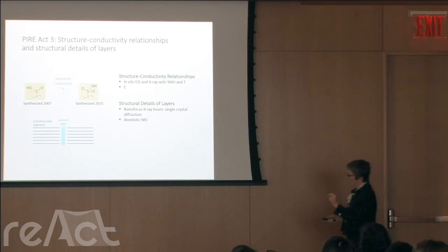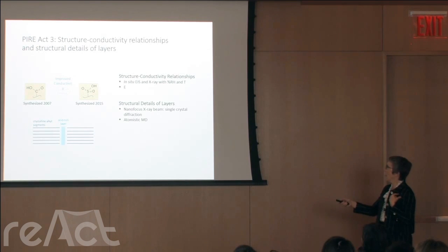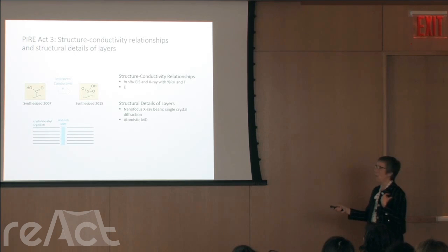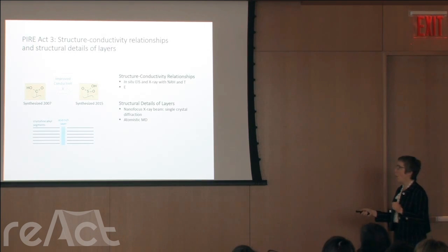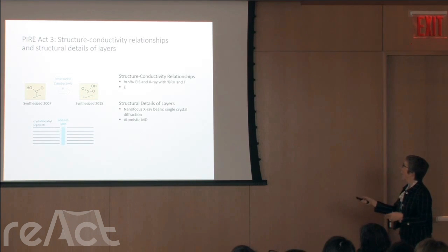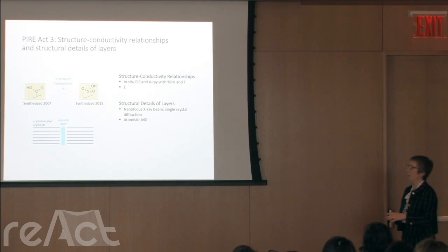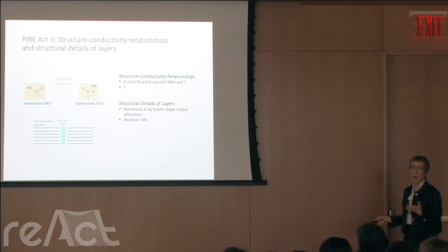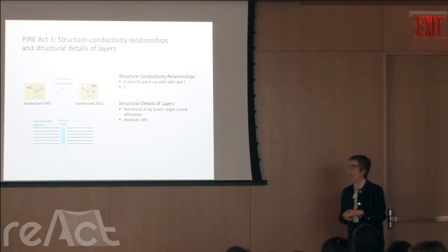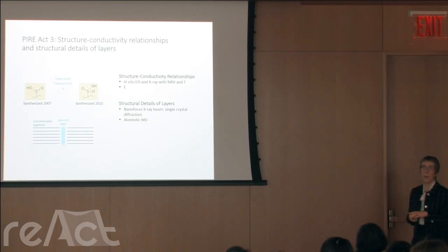Okay, and so the specific first project for Ted is to look at not the carboxylic acids, but the sulfonic acids. We know they form layers. Over the weekend, Ted learned that they actually take up a good amount of water, which suggests a certain crystal structure. And so we're planning in situ EIS and X-ray scattering as a function of relative humidity and temperature. This can be done both here at Penn, and for faster time resolution, we can do this in Grenoble. And to get a more detailed crystal structure, the nanofocus X-ray beam at ESRF within Grenoble is a fabulous opportunity to better understand these structures.